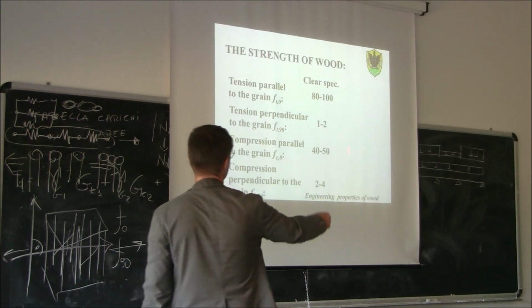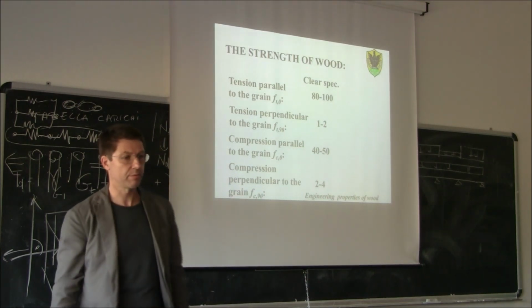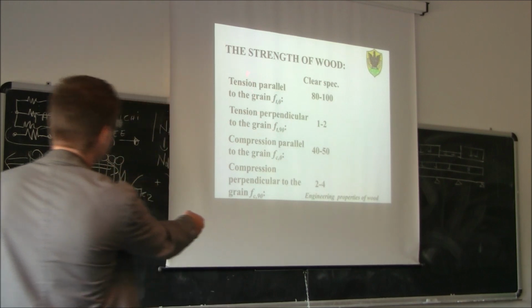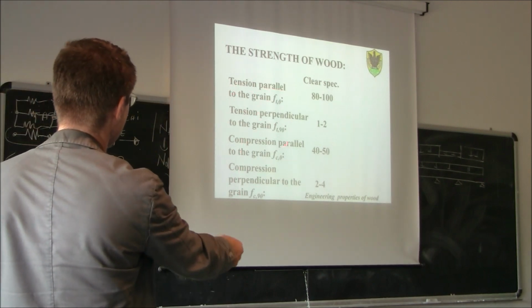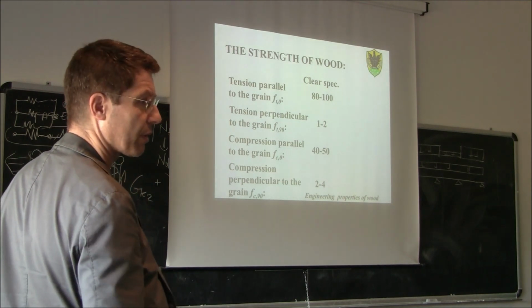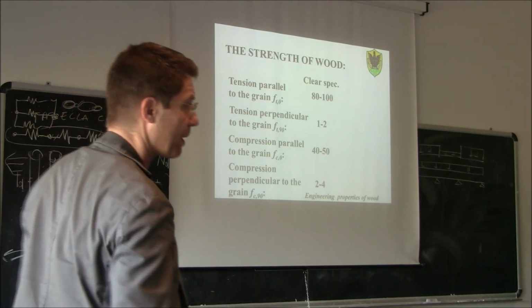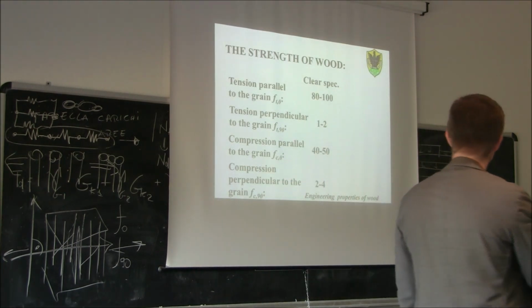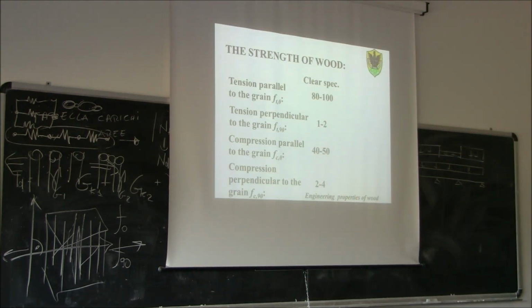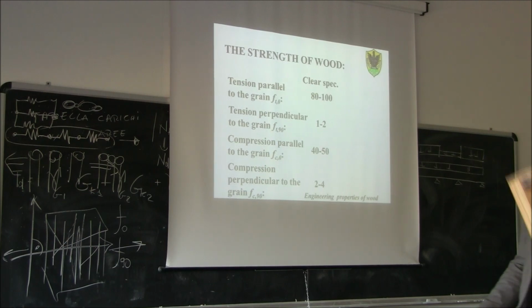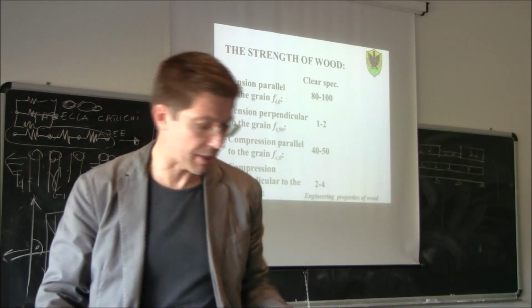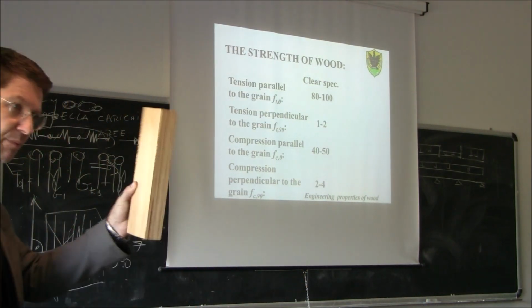So this is a summary of the properties of wood, let's say timber. Parallel, perpendicular to the grain, tension and compression, parallel and perpendicular to the grain. Clear specimen, remember, clear specimen, small specimen: tension 80 to 100 megapascal, compression 40 to 50, halfway, like we were saying before, compression perpendicular to the grain 2 to 4, and tension perpendicular to the grain 1 to 2. So this is on a clear specimen, a specimen like this. It's not a real clear specimen, because this is LVL, but anyway, a specimen like this.